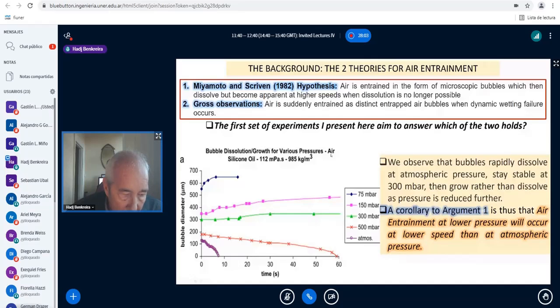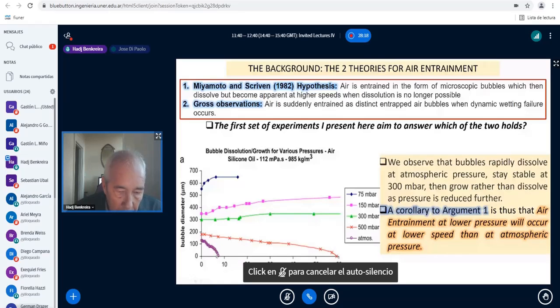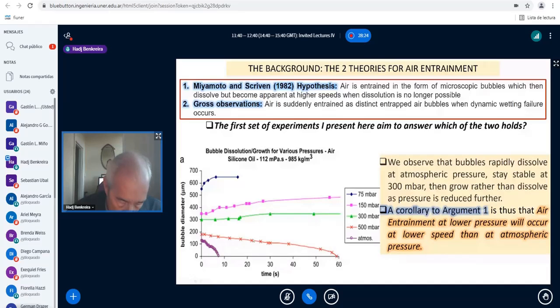So as you see in here, when you are doing it at atmospheric pressure, after less than 10 seconds, the bubbles all collapse and they're all dissolving. When you do it at 500 millibar, it takes more. It takes about a minute before the air is dissolved completely. Now, when you go at 300 millibar, the air is not dissolving into the liquid. And when you go to 150 millibar and 75 millibar, the bubbles, instead of dissolving, they were growing.